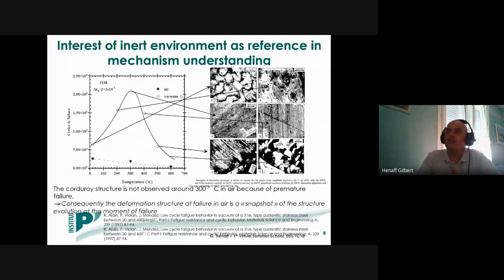So again, here is an example dealing with low cycle fatigue in the case of austenitic stainless steel 316L, deformed under cyclic plastic strain control with this value of the cyclic plastic strain amplitude. And on this graph, you have the variation of the number of cycles to failure as a function of temperature, with some data collected in air and in vacuum. And what you can see is that in air, you have a gentle variation of the fatigue life as the temperature increases. The number of cycles to failure decreases.